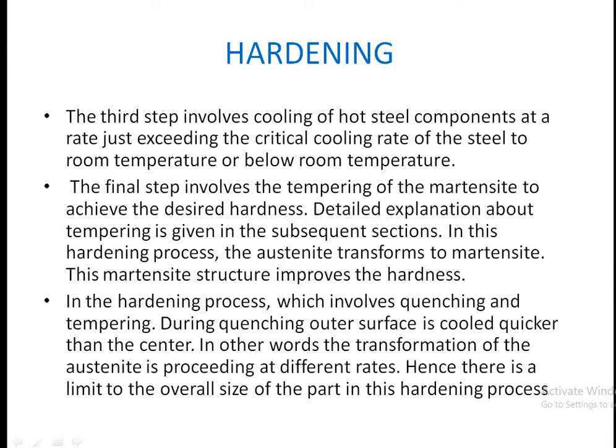The third step involves cooling the hot component, exceeding the critical cooling rate, down to room temperature or below. The fourth and final step involves tempering of the martensite to achieve the desired hardness. When you heat and suddenly cool a part, a transformation takes place — austenite is converted to martensite, which is the hardest of all the structures.